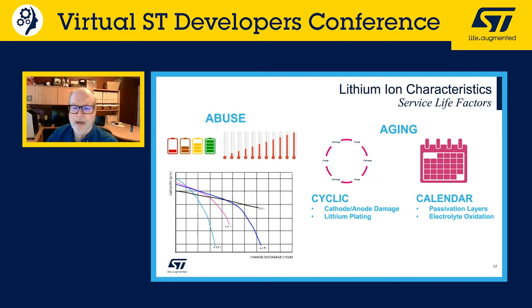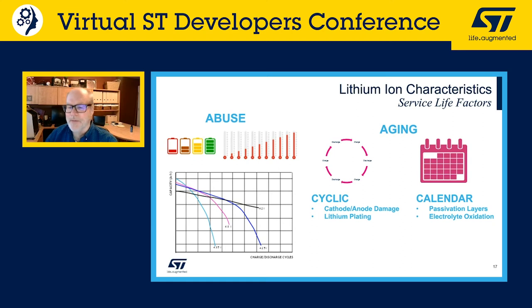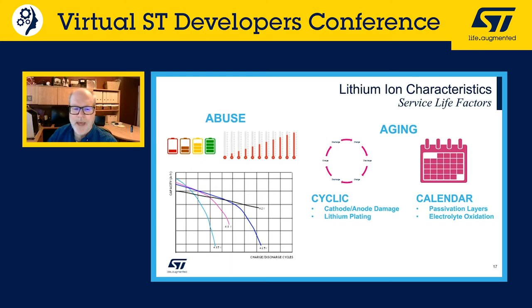The secondary category of factors impacting battery service life is associated with aging. Charge-discharge cycles can slowly damage the anode and cathode and cause lithium plating. Lithium plating occurs during charging: higher charge currents force lithium ions to move faster and accumulate on the anode, and charging at low temperatures slows the reaction rate, also causing lithium plating. Materials comprising the cell also degrade with age — this is called calendar aging — as the electrolyte can oxidize and structures like the passivation layer can degrade over time.